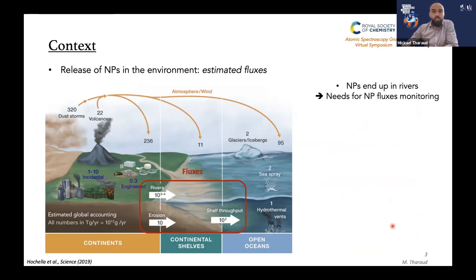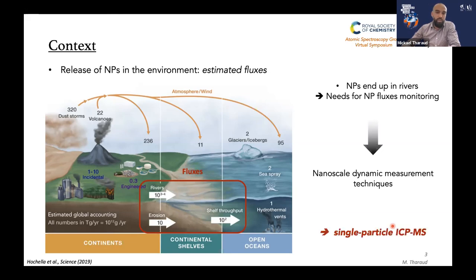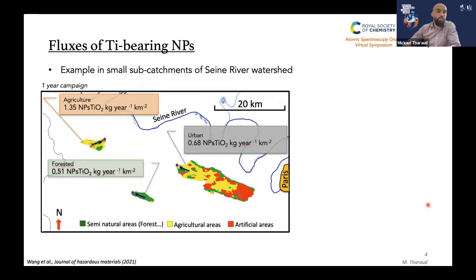And so basically what we need is to monitor the fluxes of those nanoparticles, for instance, for biogeochemistry studies or even for health issues. The idea to follow these fluxes is to have some dynamic techniques that are able to measure nanoparticles at nanometer scales. And as nicely introduced by Eduardo, single particle ICP-MS is actually one of those promising techniques that is fitting all these requirements. And so that's why in one of our studies, we tried to determine the fluxes of titanium-bearing nanoparticles in the Seine River watershed.